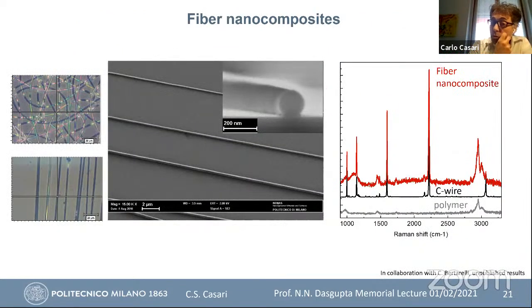This work is in collaboration with Professor Bertarelli at Politecnico di Milano, and we were also able to produce nanofibers of polymer, including this kind of structures. You can have a random distribution of aligned fibers, and from this SEM image you can see that the diameter is of the order of 100, 200 nanometers. And again, by Raman spectroscopy, you can recognize the polymer alone, the carbon atomic wire before the insertion, and in the nanocomposites you see both, the polymer and the carbon wire.